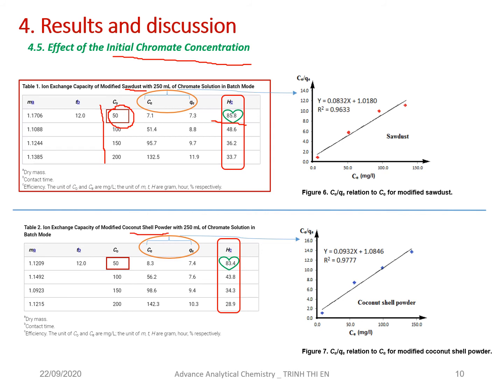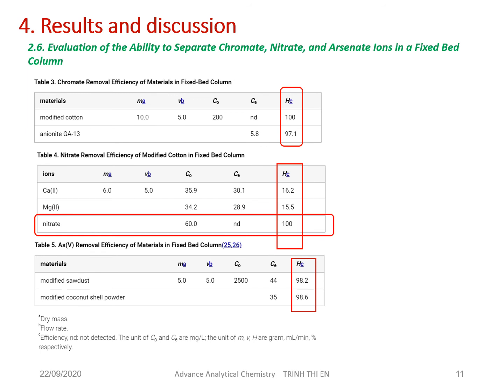And the same result with the survey with the coconut shell powder and the initial chromate solution: the maximum efficiency is at 50 milligrams per liter here, which is the highest efficiency. And then the author evaluates the ability to separate chromate, nitrate, and arsenate in the fixed-bed column. It means putting the material in a column and pouring the water through the column, and comparing the efficiency of removing chromate